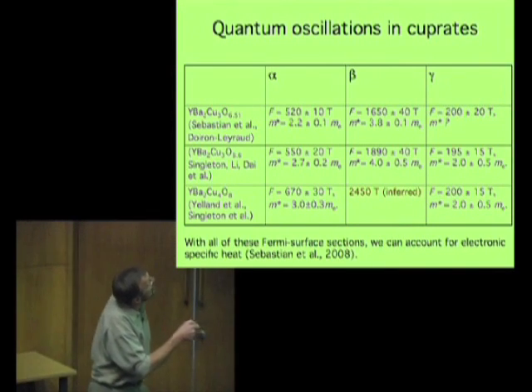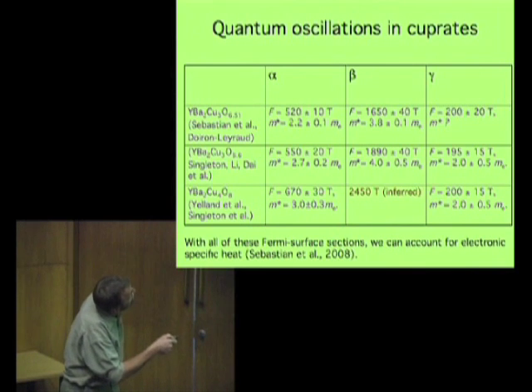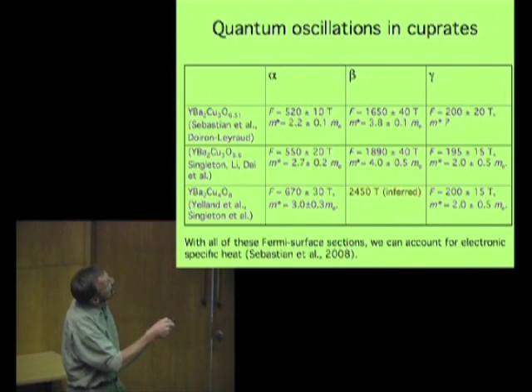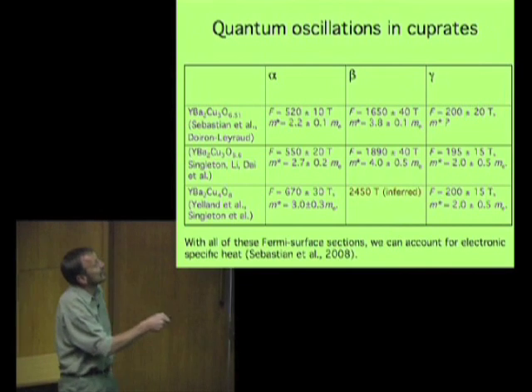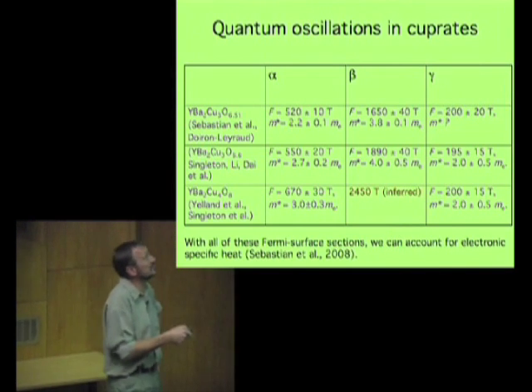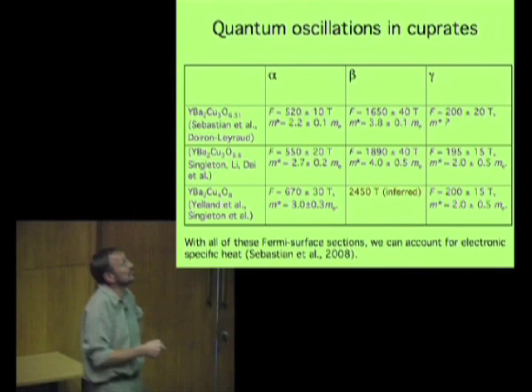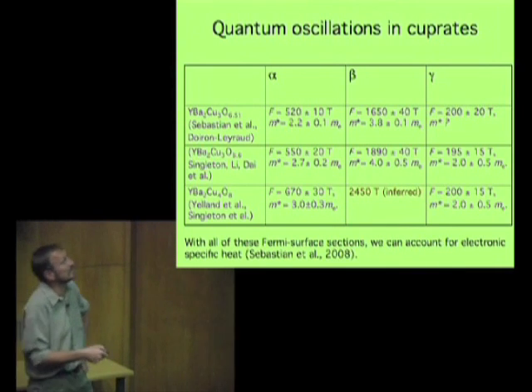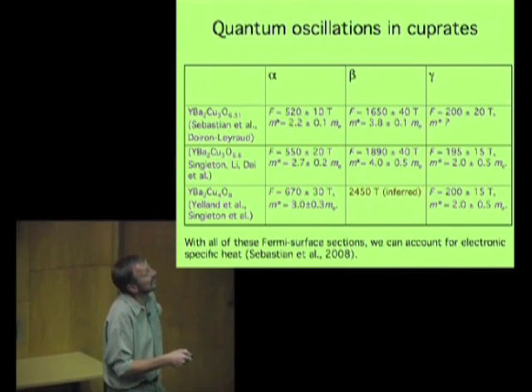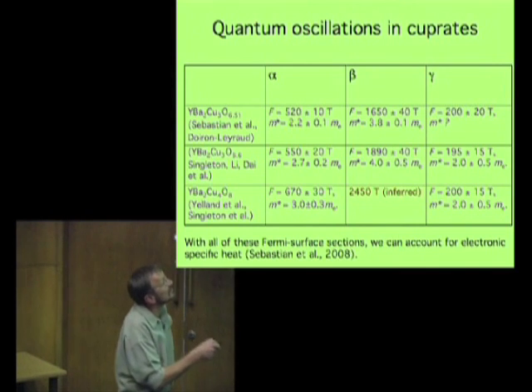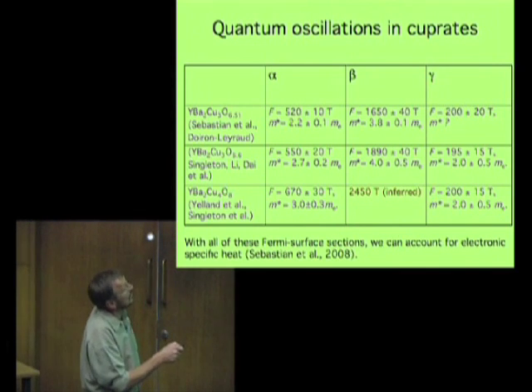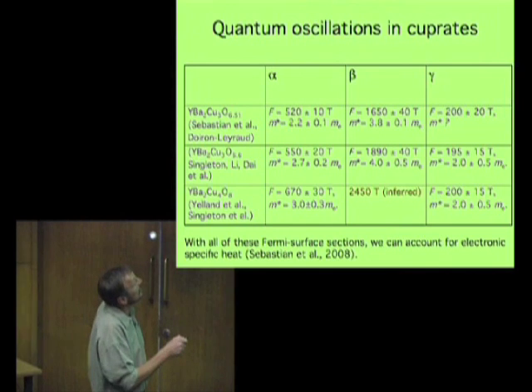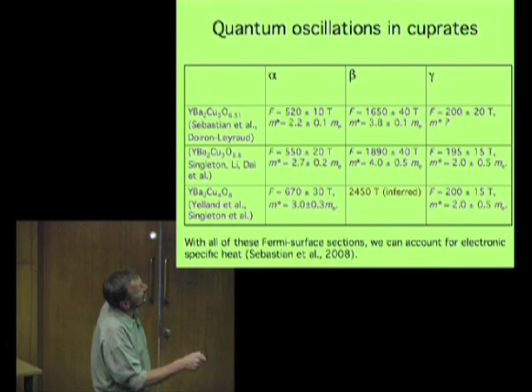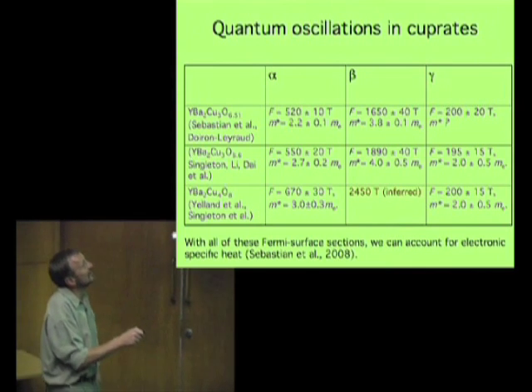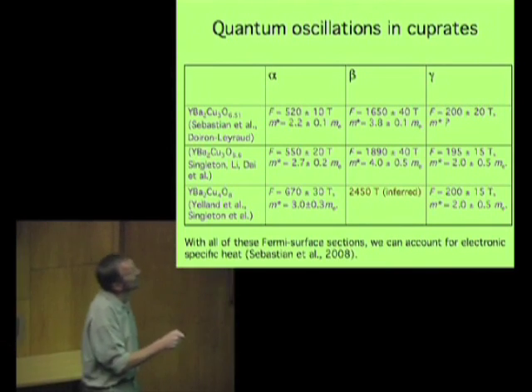As we change the oxygen in these various different cuprates, we're increasing the number of holes that there are. So we would expect the Fermi surface, as the number of quasiparticles grows, to get bigger. We would expect the frequencies that we see to get larger. And these are the frequencies that have been seen in the various experiments that have been done so far. Not at all logically, they're called alpha, beta, and gamma in not increasing order of frequency. It's in increasing order of discovery.